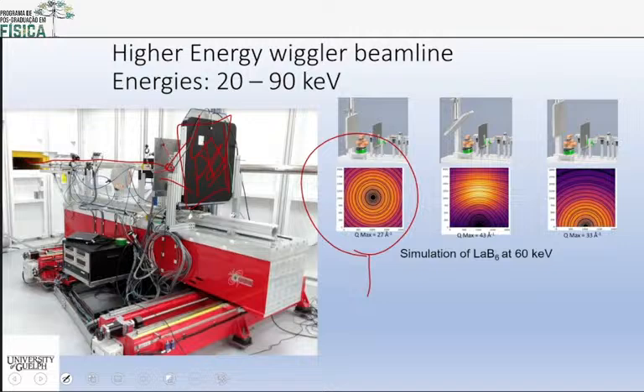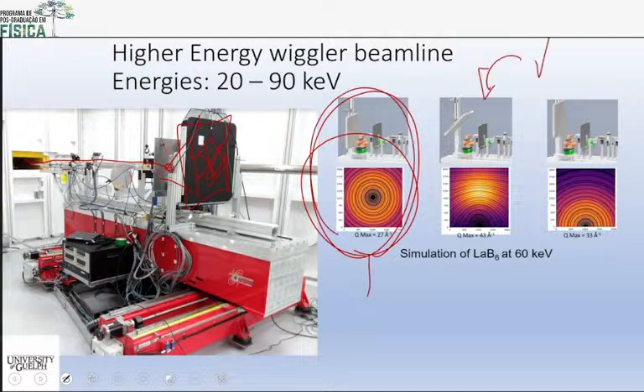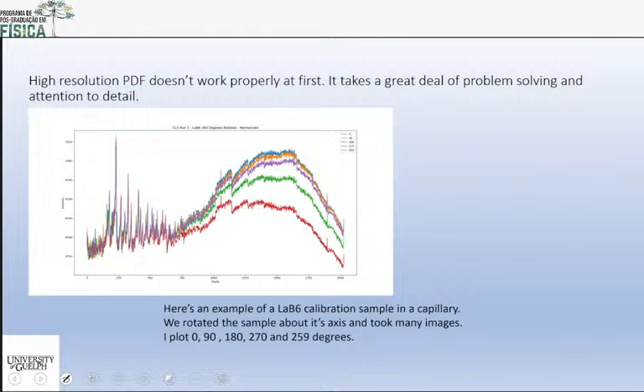And that's what I call the traditional geometry for diffraction. And that's this picture here on the left. But this is what we do. We put the detector at an angle. See that angle? And that distorts the pattern enormously, but it really improves the quality of our data. Because what happens is it amplifies the signal at really high angles or high Q, where usually you have no intensity. Now, when we first measured our patterns of some samples, this is what we got.